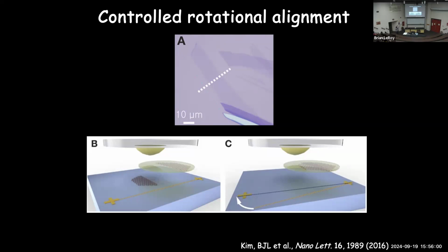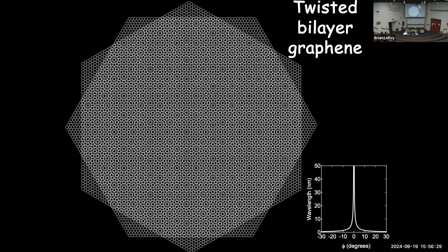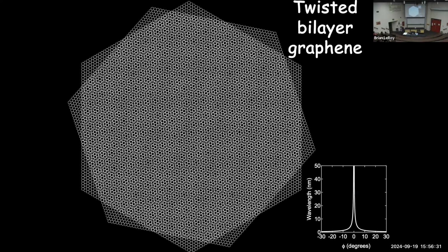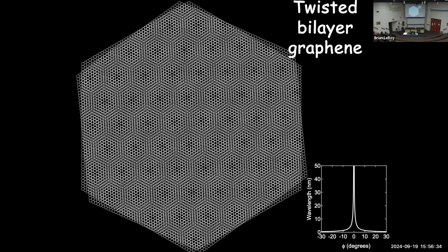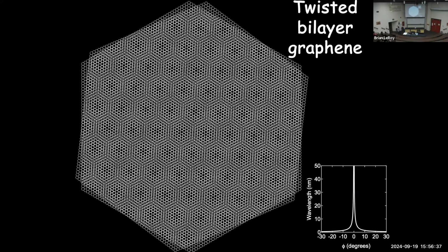We pick up this first one onto the stamp, and then we move the stamp, just a translational motion, over to here, and then we pick up the second one after some known rotation of the stage. So basically you tear one half up, move over, rotate some amount, whatever rotation angle you want, and you pick up the second one, and therefore you have the two pieces on top of each other. And so what that looks like here is that you have these two layers, and as you twist them, you can see their properties are going to change in terms of what the stacking looks like.